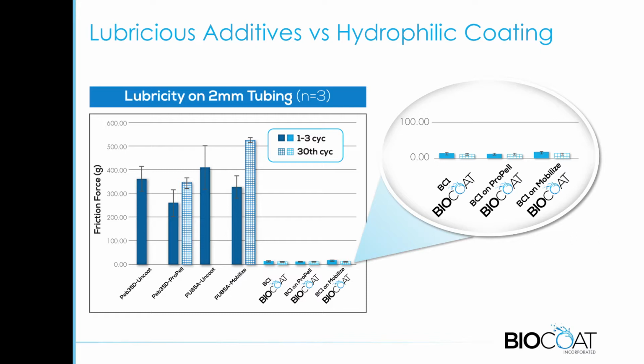So let's look at some additives and then finally some evaluations of hydrophilic coatings. The first part is some lubricious additives that can be added to the extrusion to minimize the friction. This is an example of data that we had generated where we have some completely unmodified polyurethane and Pebax tubing, as well as ones that have these low friction additives added into the extrusion.